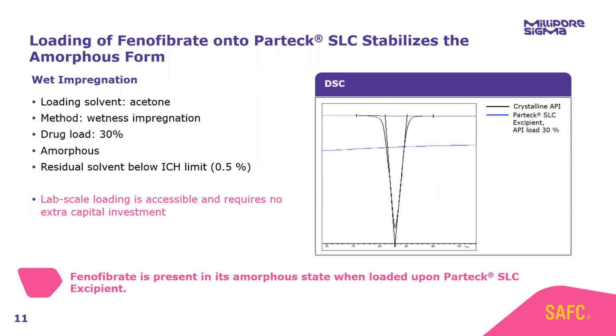So here's the case study. We took fenofibrate, which I'm sure you're all aware is a standard BCS class 2 compound that is regularly used in the scientific literature. We dissolved fenofibrate in acetone, and we used a wetness impregnation method to load fenofibrate onto silica. And if you'd like to learn more about what that is, again, please get in touch. And as you can see from the right-hand side with our differential scanning calorimetry curves, we have crystalline fenofibrate in black with its characteristic melting endotherm, the downward spike. And then when we have fenofibrate loaded onto mesoporous silica in blue, we no longer observe that characteristic melting endotherm, which means that we have successfully stabilized fenofibrate in the amorphous form.